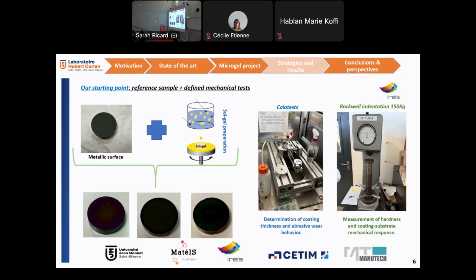Calotest is a kind of mechanical test where you can measure the thickness of the sol coating on this metallic part. We are using this ball, and with the mark that this ball presents in our sol, we are able to measure the diameter to know our thickness, and we can see the abrasive behavior of this mechanical test. We are using Rockwell indentation with 150 kilograms to measure the hardness of this sol coating and metallic substrate, and we can see the mechanical response.